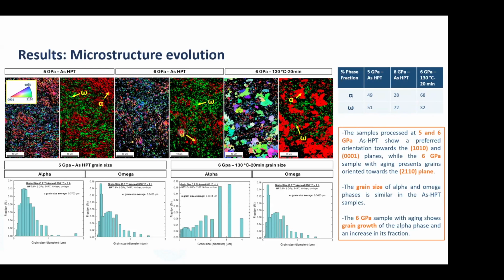It's difficult to do EBSD at such fine grain sizes because the grain size is quite small, so the noise or resolution of the EBSD is not the best. So looking at these omega and alpha crystal structures at higher magnifications using advanced crystallographic techniques, such as crystallography in TEM, could give us more information about this phenomenon.